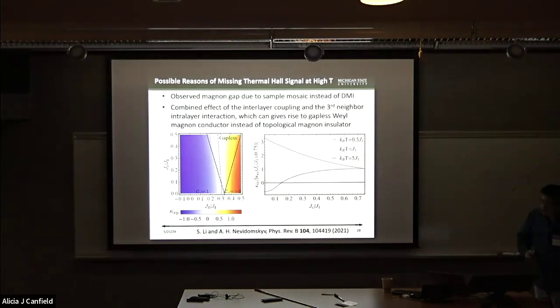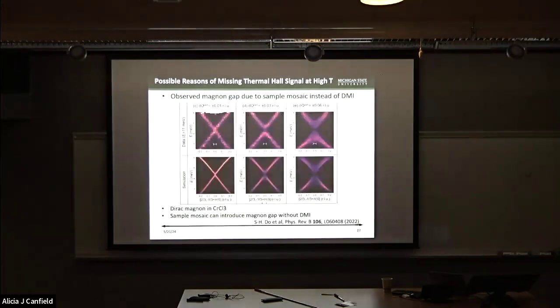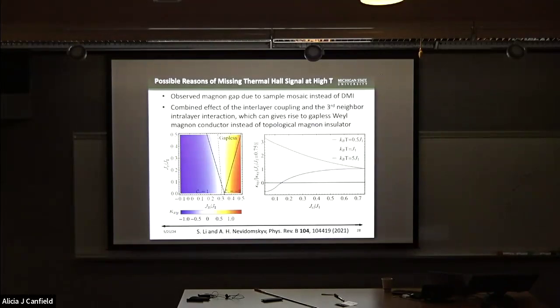Okay, so here's the potential question: is it possible that the intrinsic DM interaction in chromium triiodide is smaller than 0.09 meV? It was initially argued based on the universal neutron scaling results. Another potential reason is that it may be related to the combined effect of the interlayer interaction and the further-neighboring intralayer interaction.